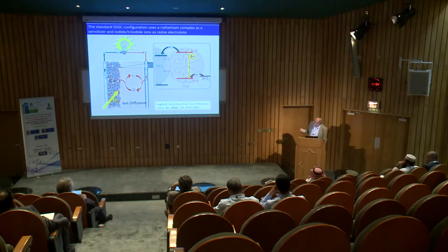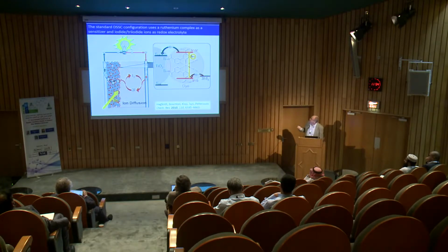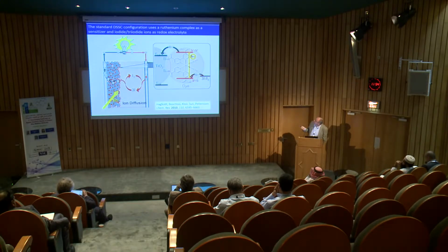And I would say the state-of-the-art system from 91 and about 20 years has been this type of mesoporous TiO2 iodide electrolyte, and this is the famous dye also prepared by Professor Nazeeruddin, also in the audience, and will give a talk tomorrow. It's called the N719 dye, Nazeeruddin's 719 dye. It's a ruthenium complex with bipyridyl ligands. You have the carboxylic groups which are attached to the surface chemically, and these ligands turned out also to be very successful to redshift the absorption and also involved in the electron transfer to regenerate the dye.